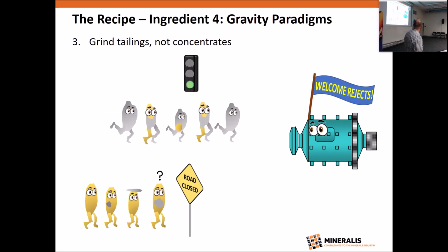Number 3, grind tailings, not concentrates. We had to sort of give a bit of thought as to why you do this when I was writing the paper. And it's unlike magnetic separation or flotation, where you can make a really rough concentrate at a high recovery before you regrind to provide that liberation for final cleaning. Gravity processing will separate the liberated minerals in the feed, and the composite particles will report to middlings or tailings. And the reason for the difference is that magnetic separation will, flotation can, but gravity processing cannot recover poor quality composites.